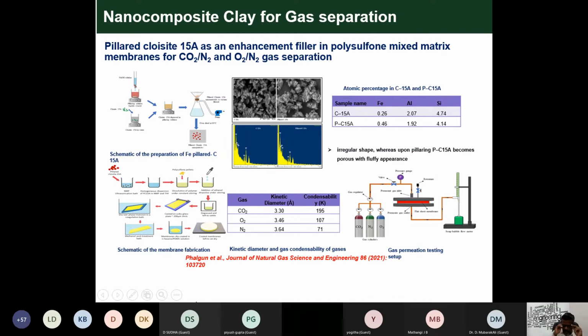Similarly, we started a very low cost membrane, an Indo-UK project from the Royal Academy of Engineering for 50,000 pounds. To make this low cost membrane we used locally available clay. The local clay has more plasticity but does not have layer by layer assembly. To enable layer by layer assembly, we used a pillared clay mixed with polysulfone as a mixed matrix membrane for CO2 and oxygen gas separation. This was developed by one of the undergraduate students, Phalgun.